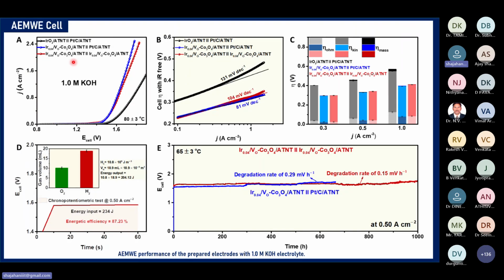And finally, we also prepared some advanced bifunctional catalyst, which is iridium doped vacancy controlled Co3O4 catalyst. So when we use that catalyst as anode and cathode, and only as anode, both are showing better performance than the commercial one: better reaction kinetics, better mass transfer, and efficiency almost reached 97.23% with the KOH solution. And for stability, if we use the same catalyst on both sides, it is acting as a bifunctional catalyst, for both HER and OER. It is showing better stability compared to only the anode side catalyst when compared to the commercial one. So stability over 1000 hours is maintained with the KOH solution.